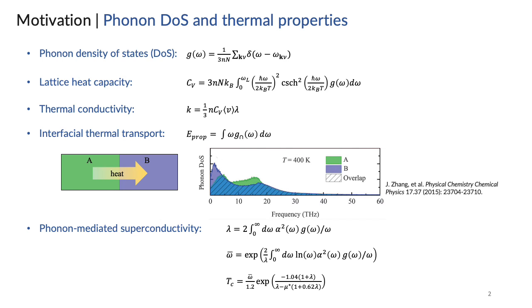The phonon density of states, or the number of phonon modes with a particular vibrational frequency, arises in the calculation of many fundamental thermal properties, for example, the lattice heat capacity, and by extension, the thermal conductivity. It also plays a key role in interfacial thermal transport, where the overlap of the phonon densities of states of two adjacent materials determines the energy propagation by phonons of a certain frequency. Finally, the phonon density of states influences the critical temperature in phonon-mediated superconductivity.